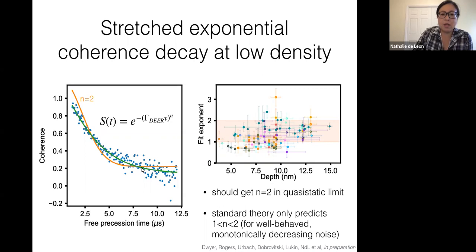One of the few nice things to come out of quarantine was that we had a lot of time to reanalyze very old data. So we went back into our historical data sets, and we were also talking to collaborators in the Lukin group, in particular Bo Dwyer, Ilana Urbach and Dolev Bluvstein, and started fitting these things more carefully and convinced ourselves that indeed all of these exponents didn't make sense, and many of them were quite low.